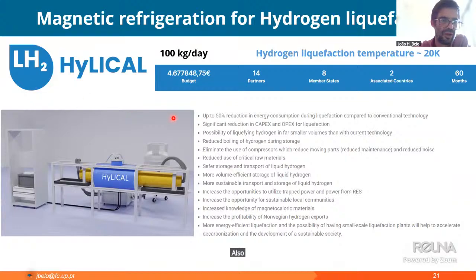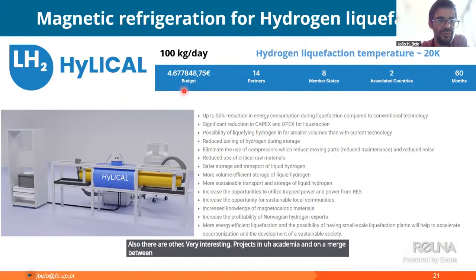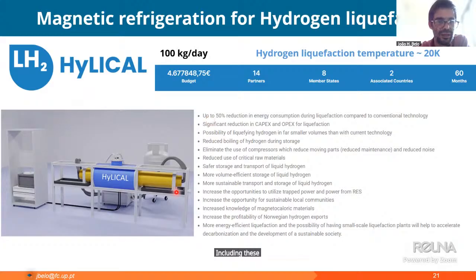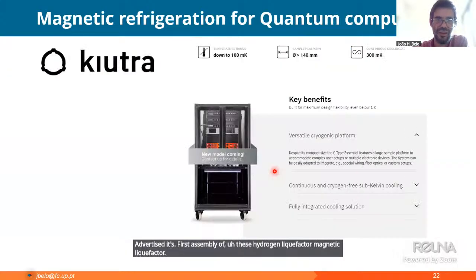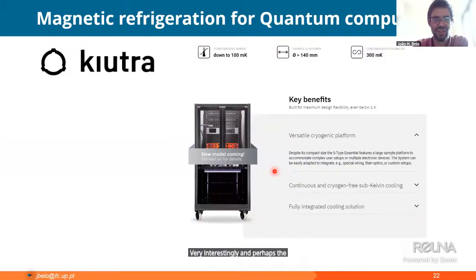Also, there are other very interesting projects in academia and on a merge between academia and industry, including this HyLICAL. HyLICAL is expected to be a hydrogen liquefactor using magnetic refrigeration principles. So hydrogen liquefies at 20 K. And in fact, just 2 weeks ago, this project showed and advertised its first assembly of this hydrogen liquefactor, magnetic liquefactor. Very interestingly, and perhaps the oldest application of these effects is indeed on the cryogenic range.